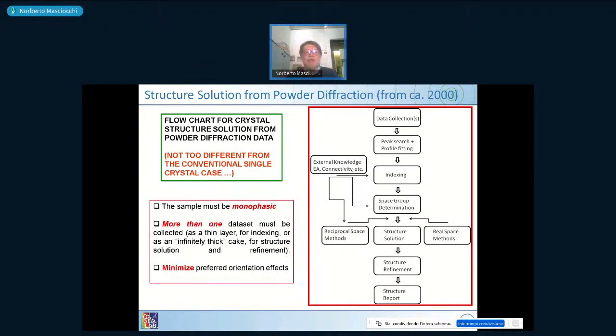There is a procedure for structure solution from powder diffraction, which is now nearly 20 years old. The procedure may change depending on the type of material you have. So it's different if you use ionic, pharmaceuticals, organic, or polymeric materials. But it's very important to know that this sequence is not a sequence of steps which takes you to the goal; sometimes you must go back several times, in a feedback manner, to see whether there are errors in the different steps which have led you into a dead end.